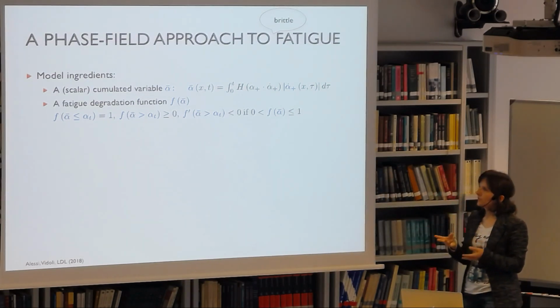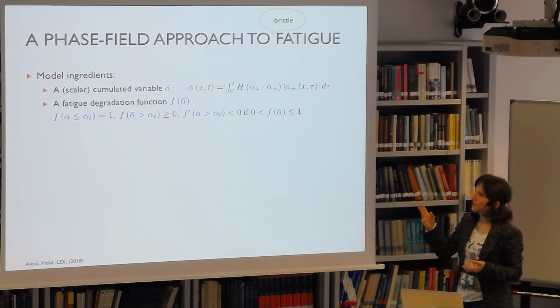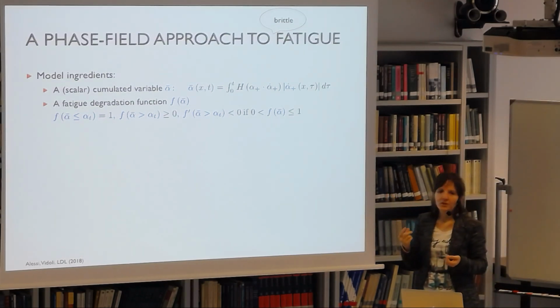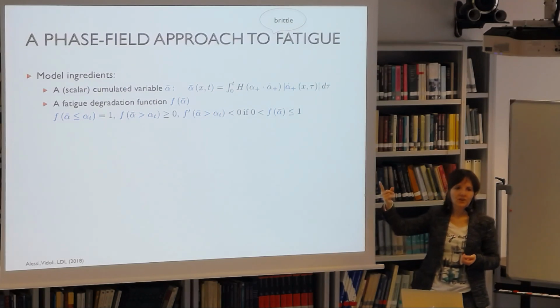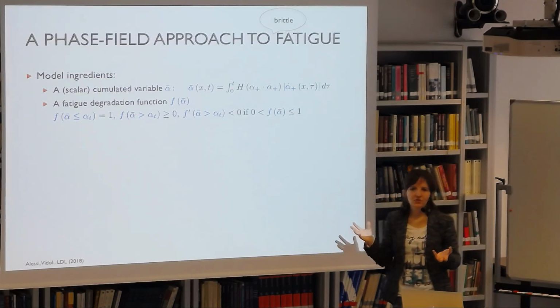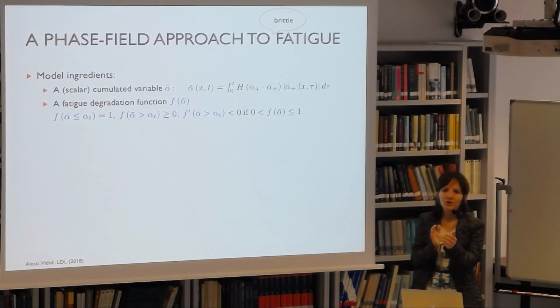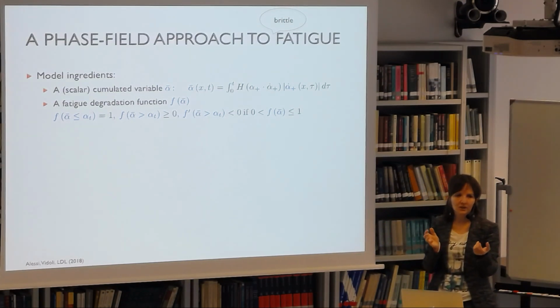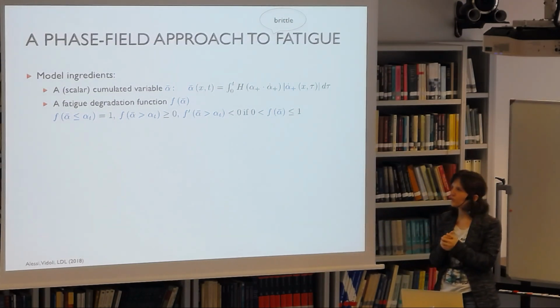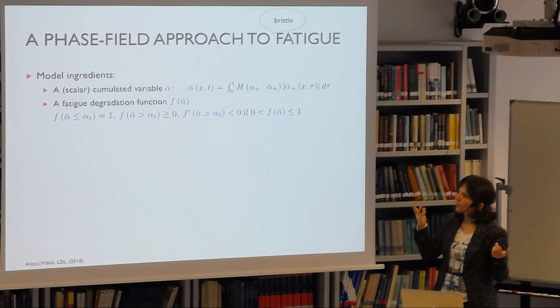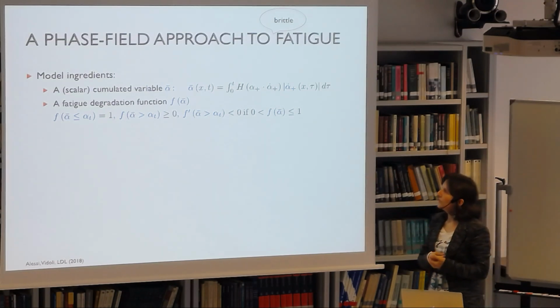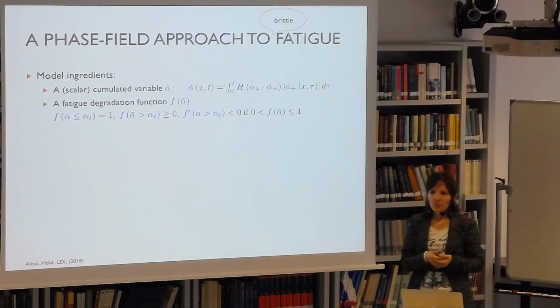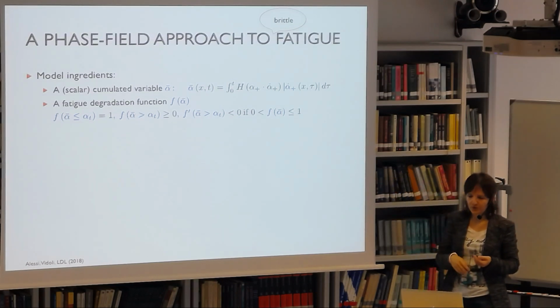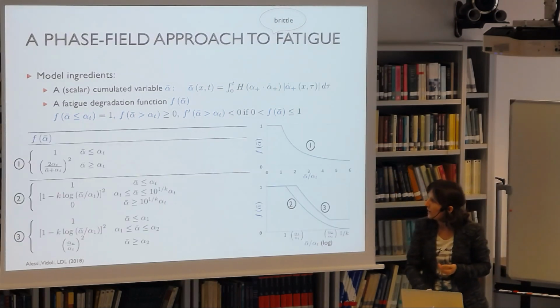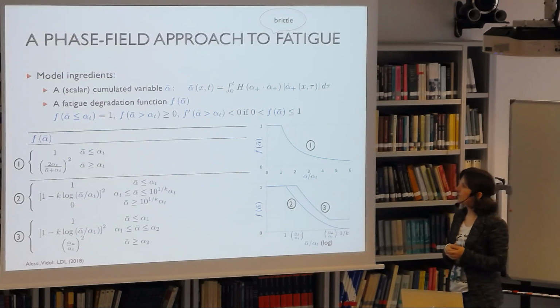Now, of course, this function must satisfy some requirements. We want this function to be equal to 1 if the accumulated variable is less than a given threshold, because we assume that below a given threshold there will be no fatigue effect. This again comes from the phenomenology, from the experiments. We want, of course, the function to be positive and to decrease, and to be always between 0 and 1. So simple choices are shown here.